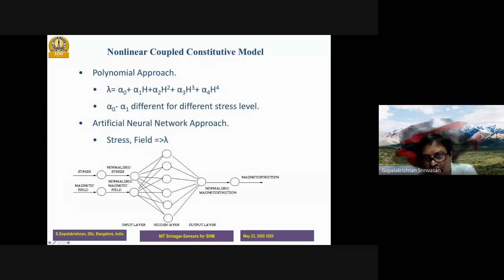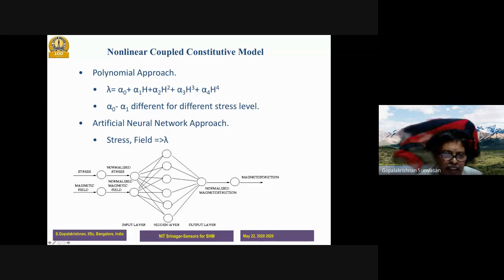So we took up to a 12th order polynomial, and we determined the constants based on the manufacturer data, so that once I have this equation, whenever I feed any magnetic field, I should get magnetostriction. From magnetostriction, I will get the stress and strain levels, I can get everything. And the second method is we created an artificial neural network where the stress levels given by the manufacturer were fed, and the magnetostriction was determined as an output using a multi-layer network. Both methods we have now done, so for any magnetic field, I can get the magnetostriction using these two approaches.